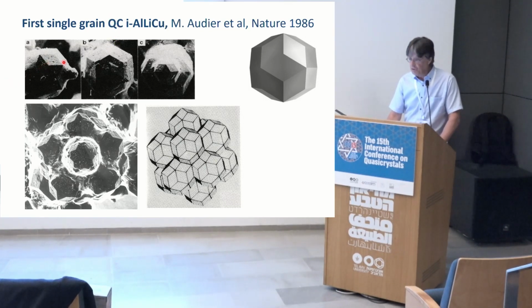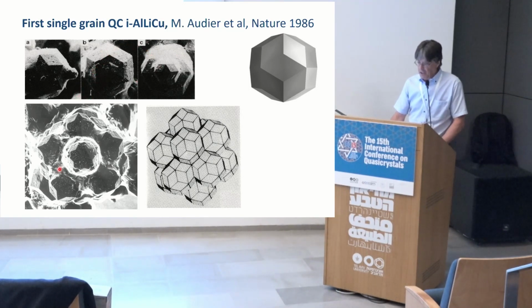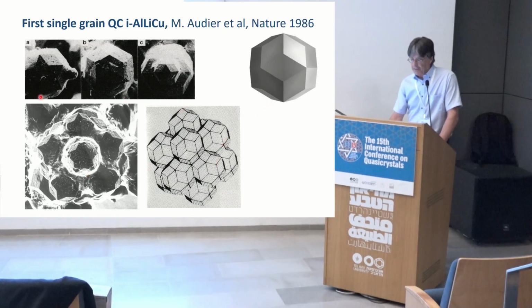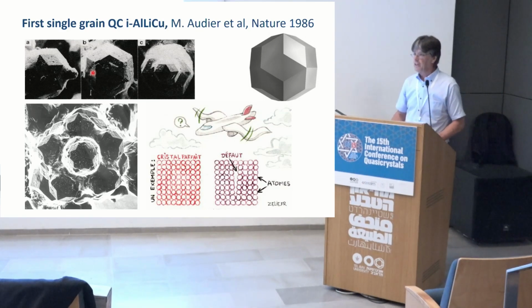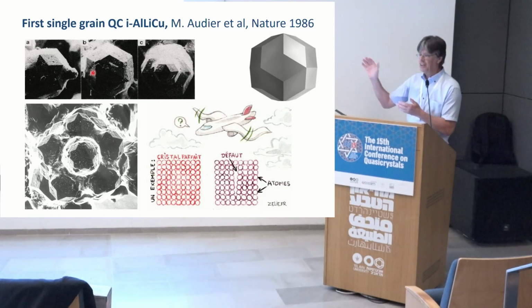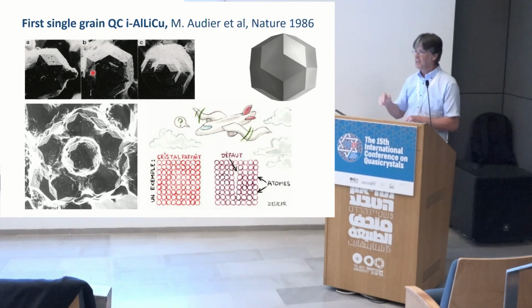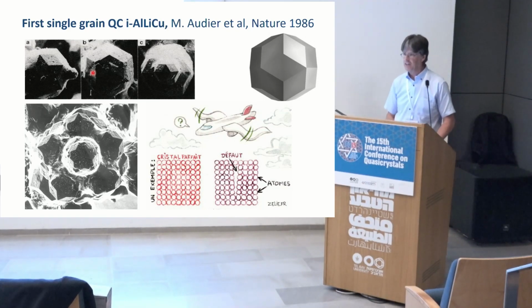So that was really a breakthrough in 86 with the nice triacontahedral shape, nice also diffraction pattern. And you see here a nice arrangement of several grains, which is drawn here. And that was the first real single crystal, single quasicrystal. In passing, that was a study done by Pechiney for aluminum-lithium alloy to have light wings made of aluminum. So it took 25 years, but now the Airbus A380 and A350 have wings with aluminum-lithium-copper alloy in them.